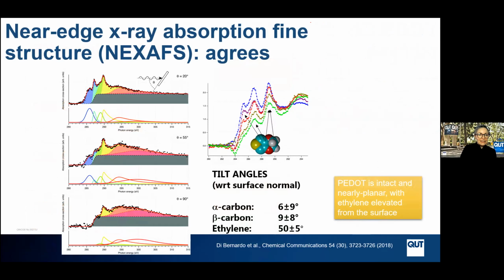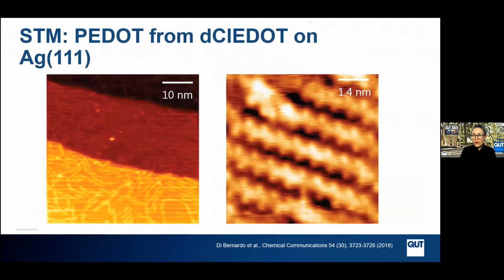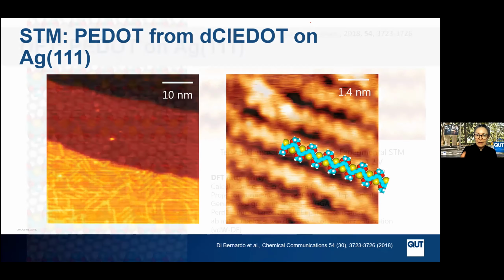polymer. They did near-edge X-ray absorption fine structure (NEXAFS) spectroscopy on the surface to confirm that the molecule was lying flat on the surface. So this was good. It's the orientation we wanted because the outcome that we were looking for here was this flat polymer. When we took the molecule home and did the same experiments in our STM system, we were able to observe that everything we had measured at the synchrotron indicated the polymer we created was the one we wanted, and our STM confirmed that. This flat-lying polymer then, of course, has the benefit of extremely long conjugation lengths along its backbone.